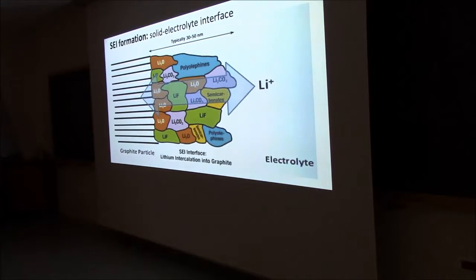Now, what's the problem which is occurring in batteries? It's at the interfaces. So in oxides, we really like to engineer the interface to look for really new phenomena. This is a terminology which is coming back in batteries continuously. So if you have the graphite, for instance, on the left, you have the liquid on the right, at these interfaces all kind of reactions are happening while you're using your battery. If you make your stack of materials for the first time, when we do that in the lab, and we start to charge and discharge, so you move your lithium in here and back, that's when you form this layer in the beginning.